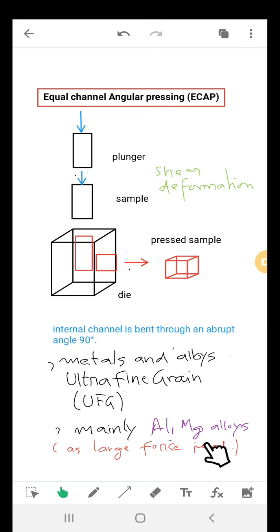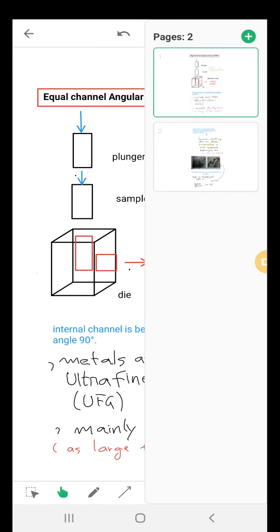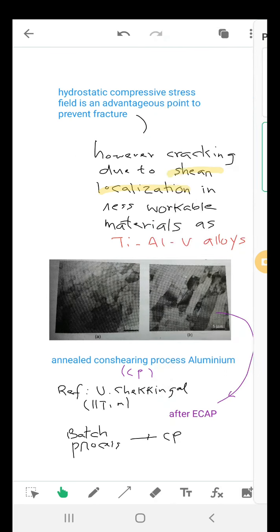The reason is that a large force is required through the channel die to overcome the large flow stress and frictional stress. The hydrostatic compressive stress field in ECAP is advantageous to prevent fracture.